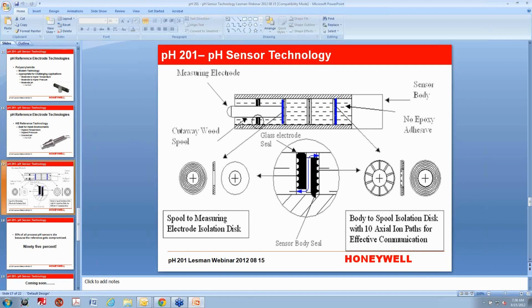The front one, there's a front piece that's Teflon, and then you have 5 wood sections, and in between these wood sections, there are wooden dowels that have a hole drilled in the middle for the glass stem to come through. And in between each of these wooden dowels is a set of Viton seals, and these seals are sized such that one seal seals up against the glass, but not against the body, and the other one doesn't seal against the glass, but it does seal against the body.